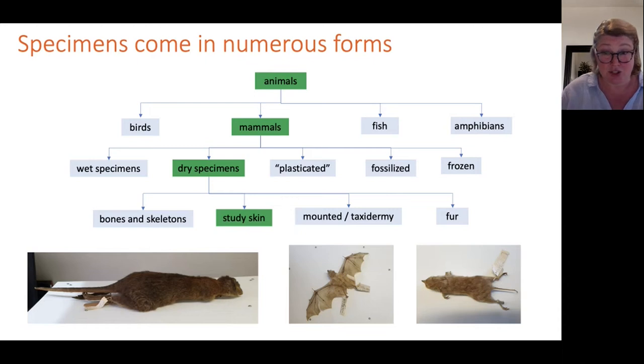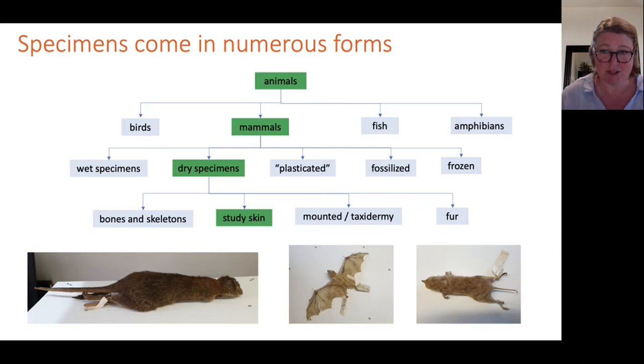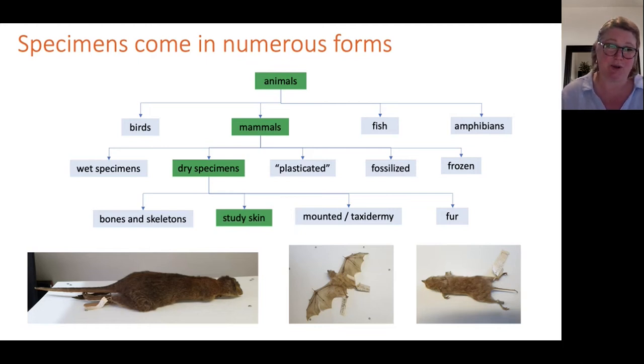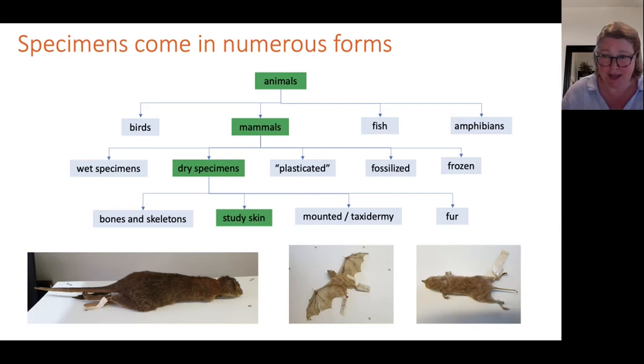I also chose study skins which, while more likely to have contamination from the museum storage environment, are less chemically altered by the rehydration and mounting process. I found I could create a statistically acceptable rate of variation with only 18 sample spots on mammal skins, compared to 45 spots on mounted bird skins. My next round of data collection will confirm whether that holds.